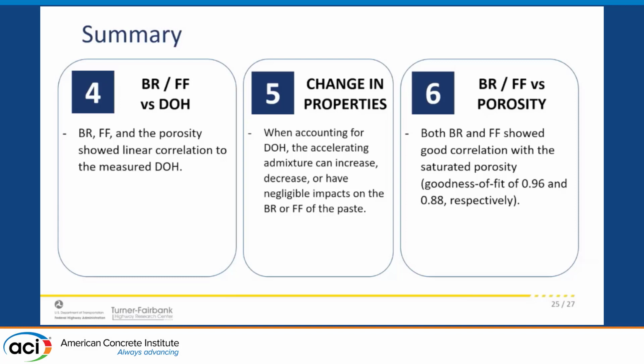And the good news is that both bulk resistivity and formation factor have good correlation with the porosity. So they can tell us useful information on the quality of the transport properties or the microstructural features of the system in case we want to apply them for quality control in repair applications.